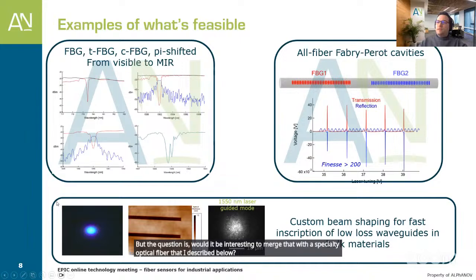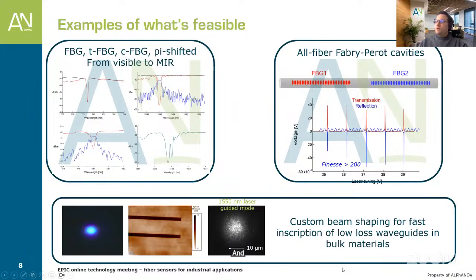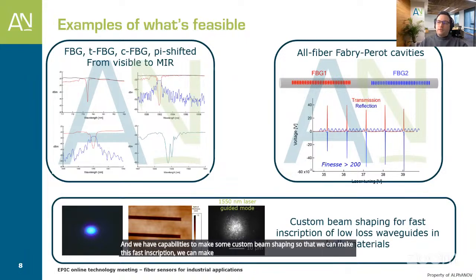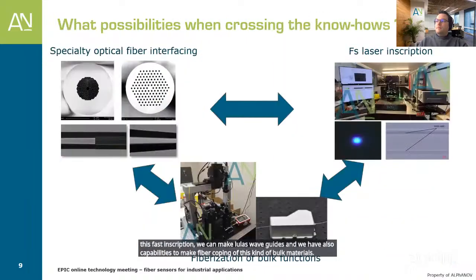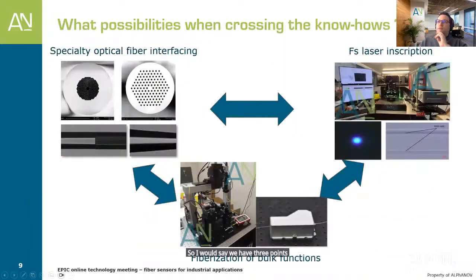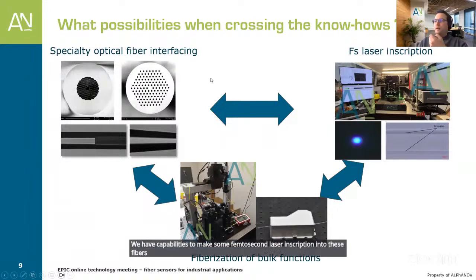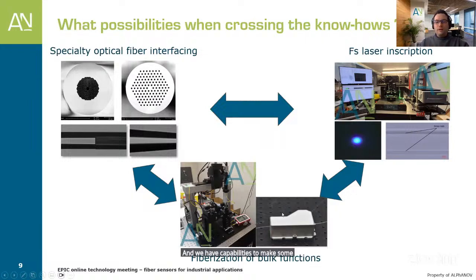And the third point is, with this kind of station with femtosecond laser inscription, you can also write waveguides in bulk materials. And with these waveguides, you can also make some kinds of sensors based on evanescent coupling of light. And we have capabilities to make custom beam shaping so that we can make this fast inscription. We can make low loss waveguides. And we have also capabilities to make fiber coupling of these bulk materials. So I would say we have 3 points here. We have the capability to interface specialty optical fibers. We have capabilities to make femtosecond laser inscription into these fibers or into regular fibers. And we have capabilities to make some coupling in between the different elements.